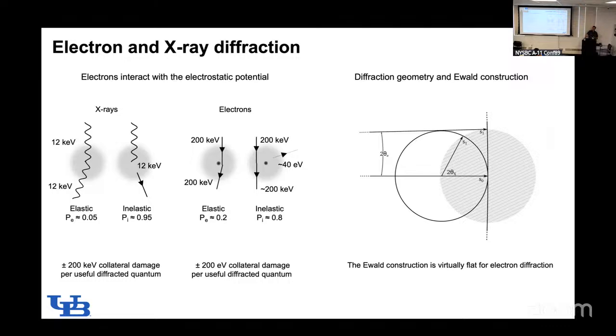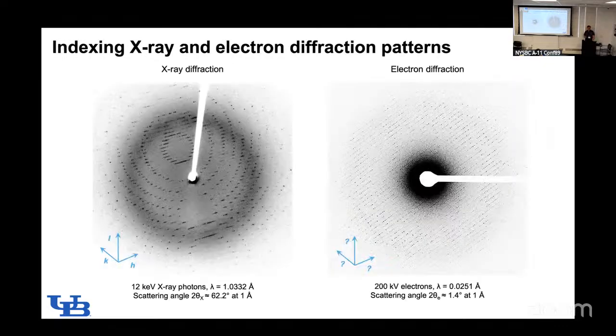The other fun thing here is your Ewald sphere. Because of the way physics works, and electrons have mass, it looks completely different. Because your electrons have mass, your wavelength, instead of being about 1 angstrom, is about 0.02 angstroms. The practicality of this is, for an X-ray diffractometer, if you want atomic resolution on your home source, you have to bring the crystal all the way up to the detector, and the scattering angle at 1 angstrom is like 60 degrees. For electrons on a 200 kV instrument, your scattering angle for atomic resolution is something like 1 degree.